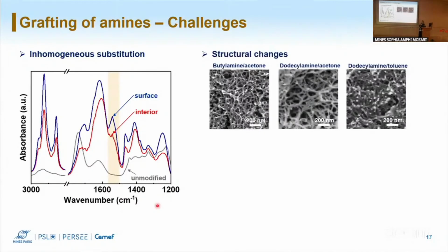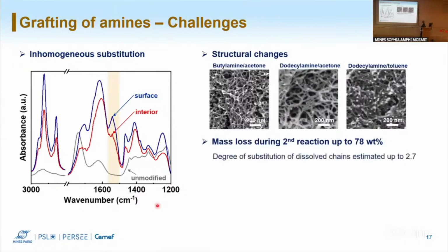So we expected to obtain at the end the same structure since we had performed already the coagulation of our material, but we saw that during the reaction our gel was changing, and this was not always good for density and thermal conductivity. And lastly, we saw that we lost a lot of mass during the modification. So when chains started to substitute a lot on the exterior of our material, they started to dissolve in the solvent. And for these dissolved chains, we could estimate a very high degree of substitution.